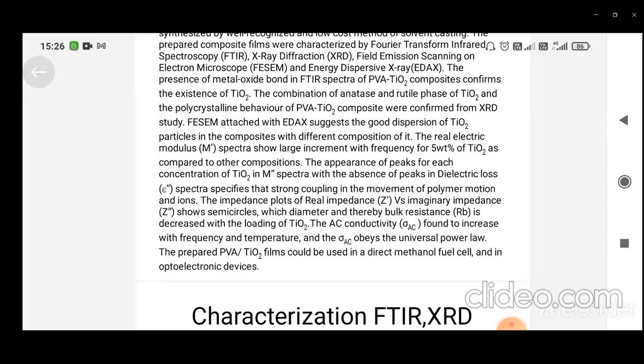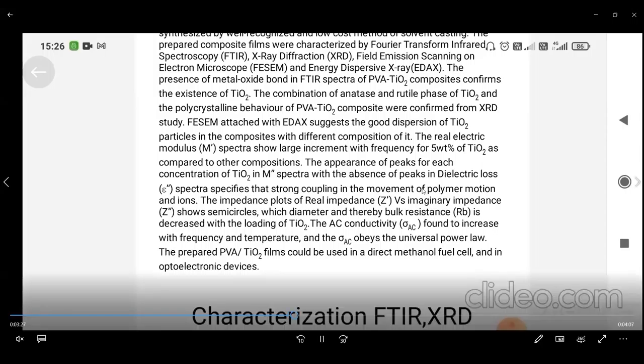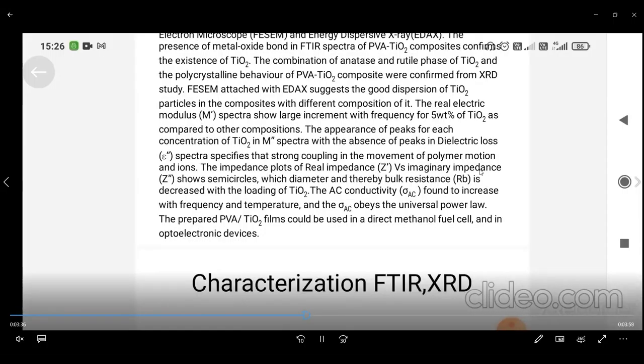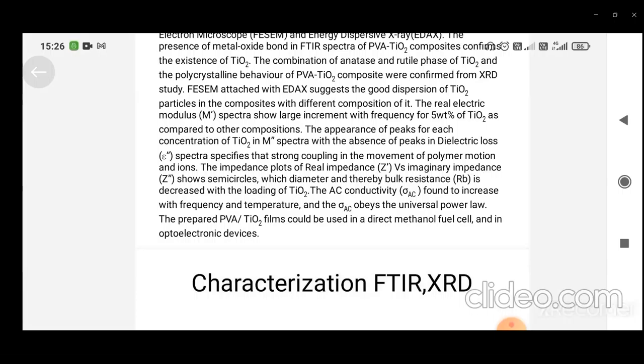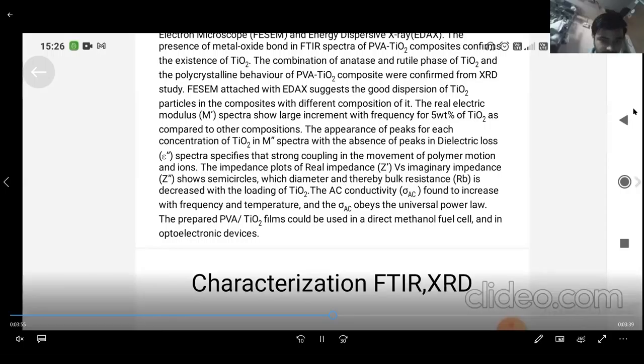The obtained homogeneous solution was poured into a flat petri dish and left to evaporate at room temperature. After 24 hours, the thin film composite was formed in the petri dish and was removed after complete drying. The synthesized film was stored in a vacuum chamber, and then used for the different characterizations. First of all, we measured the thickness of the thin film using a profilometer. The prepared thin films lie between 70 and 80 micrometers.